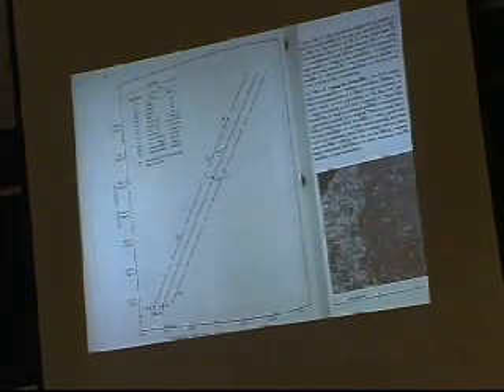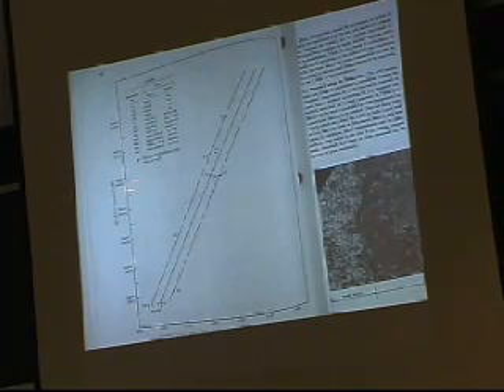In cast iron, you can get to 700 degrees preheat. Now, who wants to weld on a piece of steel that's at 700 degrees? It's like standing next to an open oven. Okay, now, when the Seawolf submarine had its problems with hydrogen cracking, with these very small little cracks in the weld metal, the initial solution to get back in service for about the first 6 months or a year was to actually preheat these things to 400 degrees Fahrenheit.